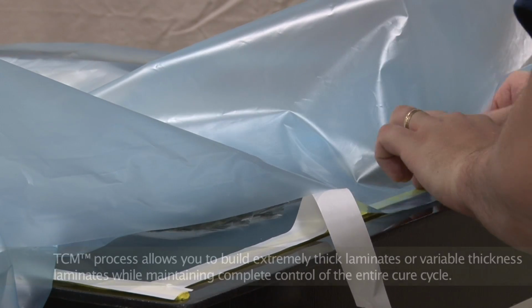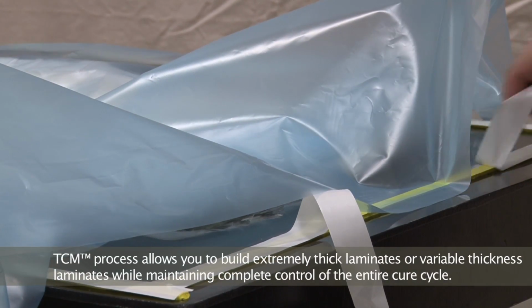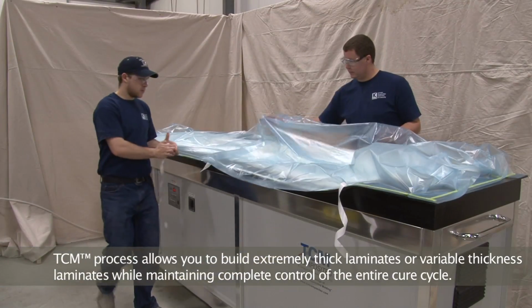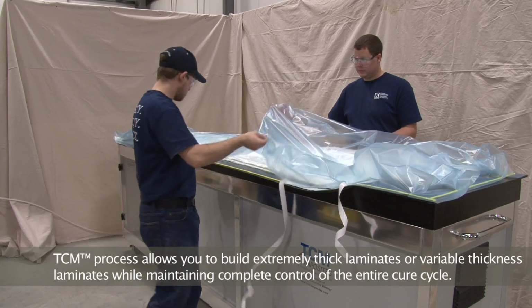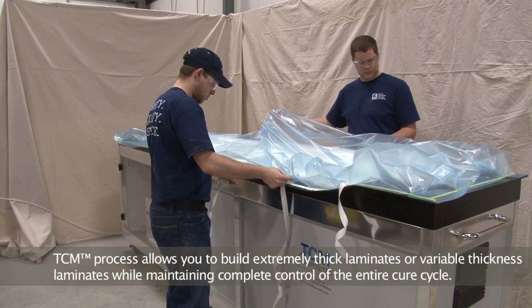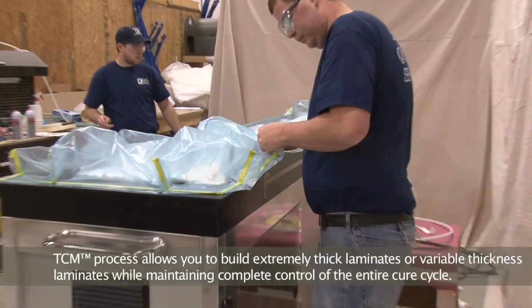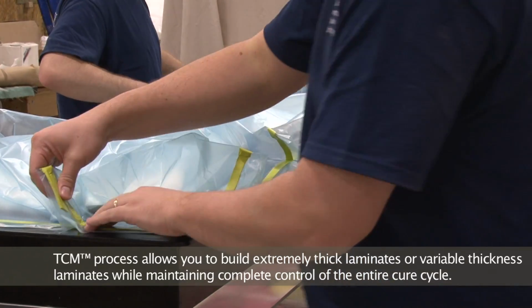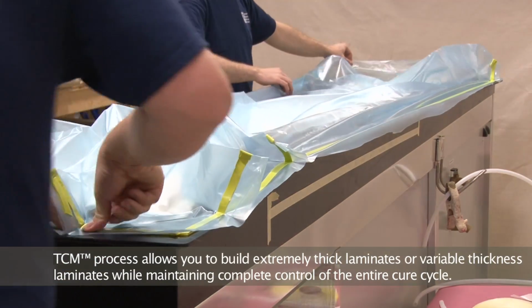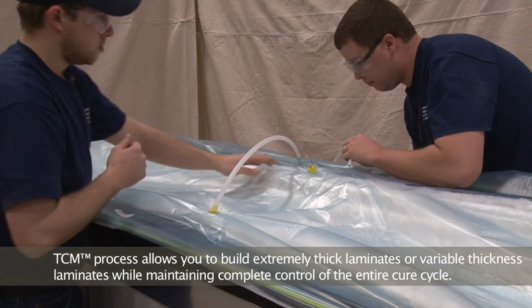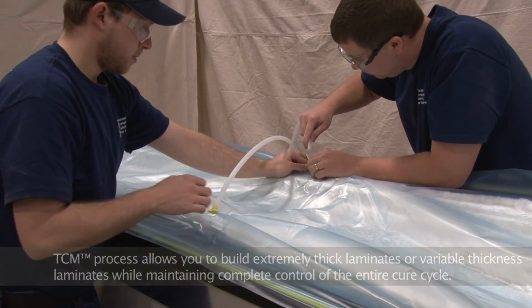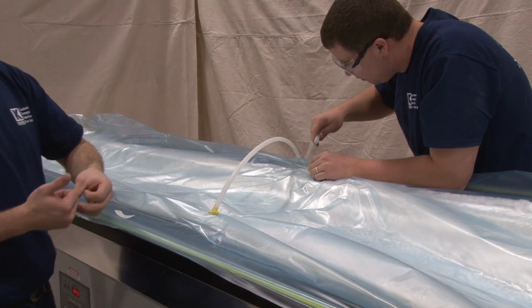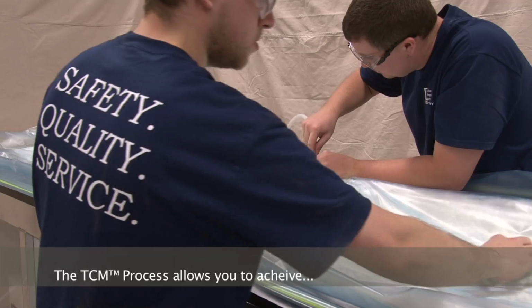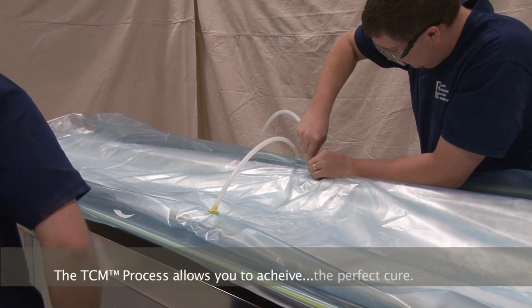We realized that we had to control the amount of input heat and then control the temperature throughout the entire process. The only way to do that was temperature-controlled molding. There's no other way, especially in thick laminations. We've done a 7.5 inch thick lamination without issue. And then we produced one part that was a wedge, 1/2 inch thick on one end and 7.5 on the other, and got a perfect cure.